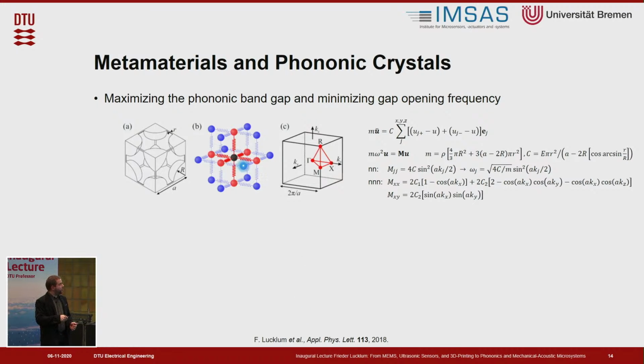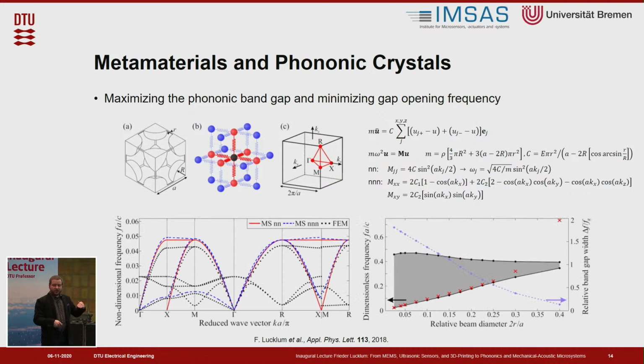And indeed, you can set up this 3-dimensional arrangement of masses and springs, look at the interaction between a single mass and its nearest neighbor or its next nearest neighbor. I won't go into the formulas, don't worry. And calculate which kind of vibrations, which kind of acoustic waves can propagate through that structure. And you will find that there's an upper limit of how the waves can propagate, which is synonymous with the lower limit of the first band gap. And this lower limit is very low, orders of magnitude below the Bragg scattering frequencies.